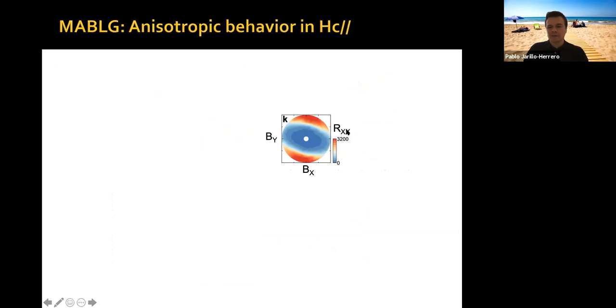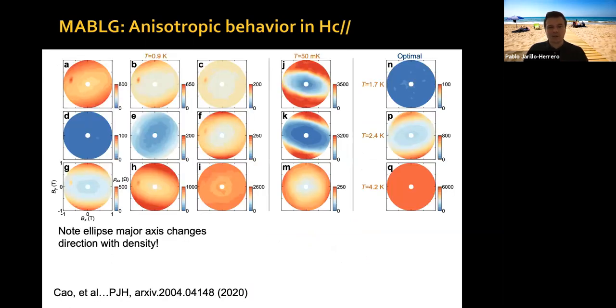Here we go. This is the resistivity versus magnetic field in the X direction and Y direction, and you can see this ellipse. You have a very different critical magnetic field when you go in this direction and when you go in this direction. Now, the nice thing again about magic angle graphene is we can do all of this. This is for a particular doping. We can do this as a function of all dopings, at a given temperature.